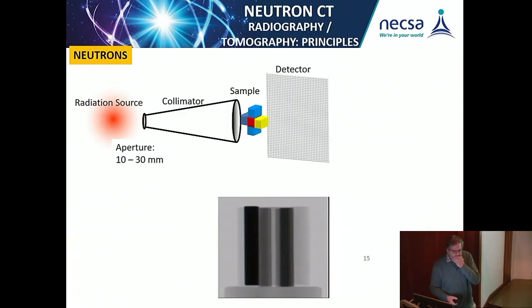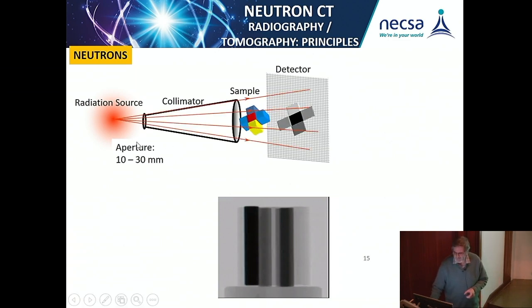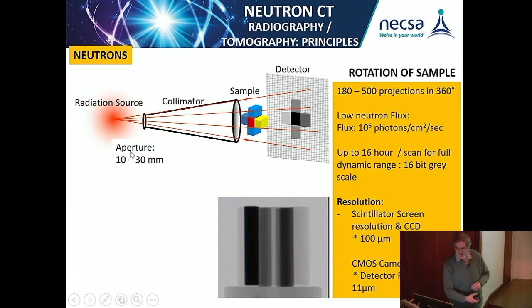Most of you are not familiar with neutrons. With neutrons, you have an aperture of 10 to 30 millimeters in size. Remember, with micro CT, you have an aperture of 600 nanometers to 1 millimeter in size. That is because the neutron flux that you have when you rotate your sample is much lower, up to 10 to the 6 photons per square centimeter per second. And then a scan can last up to 16 hours in order to achieve the highest spatial resolution and dynamic range of your sample. So the resolution here is a function of the scintillator screen.